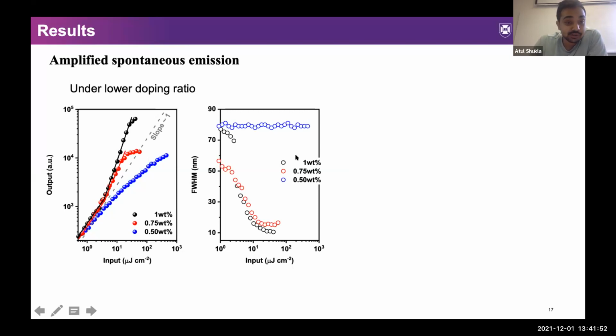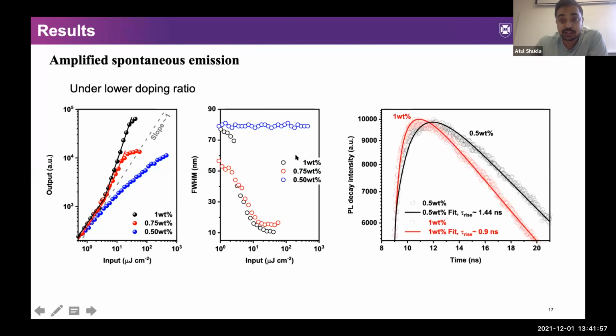So in order to really see why this happens, we did some high resolution energy transfer estimation. And we found out that the 0.5% doping shows higher rise times.